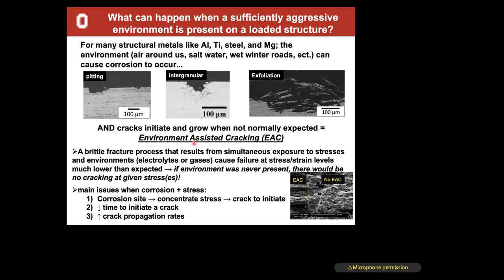And what's really happening is a brittle fracture process. So typically, as material scientists or mechanical engineers, you want to think of a ductile fracture process. What that means is you physically see the material start to change. You can see a shape change before something breaks. Brittle fracture, you don't see that change. And when you have corrosion processes, it induces this brittle fracture process. The main issue here is that a corrosion site itself can basically make the stress more concentrated. So the stress is felt more severely near corrosion, and that can cause a crack to initiate, and you wouldn't normally expect it to. It'll initiate faster, and a crack will grow at rates much faster than you expect. So when you aren't anticipating the impact of the environment, failure can happen when you normally would never get it in the first place.